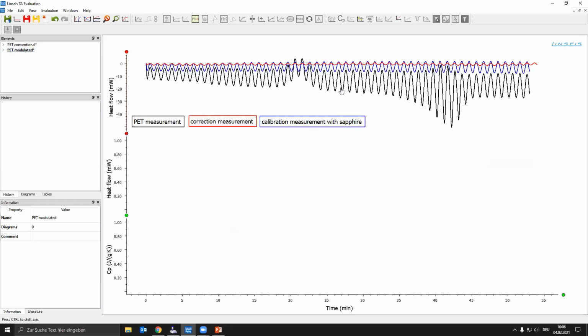Now let's go for the modulated DSC measurement. Here I've plotted in the upper part of this diagram all the curves we need. The red one is the correction curve, the blue one is the calibration curve, and the black one is my sample measurement. And just a hint, if you use just the crucible without any sample inside for the correction measurement, the amplitude will be pretty small due to the low heat capacity. With your sapphire inside, the amplitudes of your result, so the DSC measurement itself, get higher. And in this case, I've used, I think, around about 19 milligram of PET with its higher heat capacity of around about 1.5 near the glass transition.